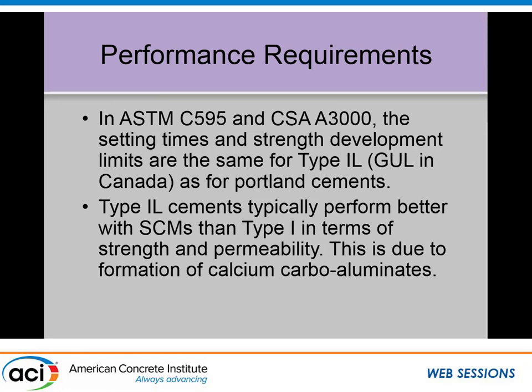And the way we've designed the Canadian standard and the ASTM C595 is that physical requirements are exactly the same. Setting time requirements, one day, through strength development curves are exactly the same. So to the user, it should be transparent. You shouldn't be able to see any negative effect of using limestone cement. So it's a bit different than the way the Europeans approached the CEM II/A-L, where they use up to 20% limestone, but their only equivalency is at 28 days. We say, no, everything's got to be the same, right? Through whatever strength requirements have to be the same. And so the companies optimize their systems with the limestone cements to get equivalent performance. So you're not suffering anything from it, just reducing the CO2 burden.